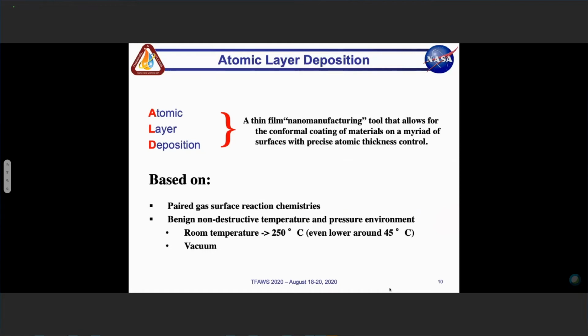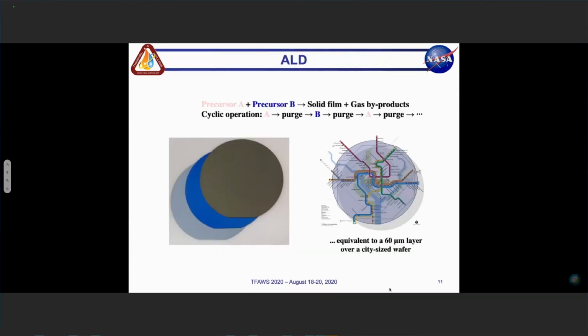The best way I like to describe this is through a basic analogy. Take a look at Velcro: it has two surfaces which allow them to stick. One is your loops and the other one is your hooks. Imagine that one of the gases creates nothing but your hook surface, and your second gas creates nothing but your loop surfaces, and you continue going down this process until you get a material which is thick enough to meet your needs. So this is what's known as a digital process. These reactions are benign to temperature up to about 250 degrees C, and you don't really need a high vacuum.